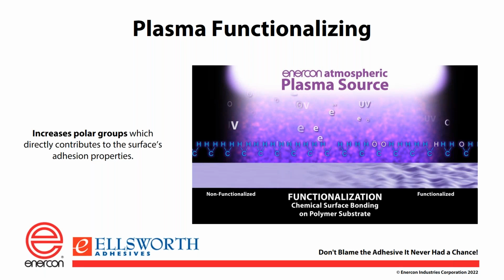Surface energy is basically related to the strength of the atoms that are holding the molecules, or the strength of the bond holding the molecules together. So if I have a block of polypropylene and I try to cut through that, all you're really doing is cutting the bonds. And that's pretty easy to do because plastics have low surface energies. If I've got a block of titanium, and I'm trying to cut it, the bonds between the titanium atoms are much stronger, and so the surface energy is higher. So we have to look at that starting surface energy to see where we're going to be and what ability you're going to have to bond to it. And then once you plasma or flame treat it, we're hoping to increase that by increasing those polar groups on the surface. And then once the bond is made, then that is a permanent bond.